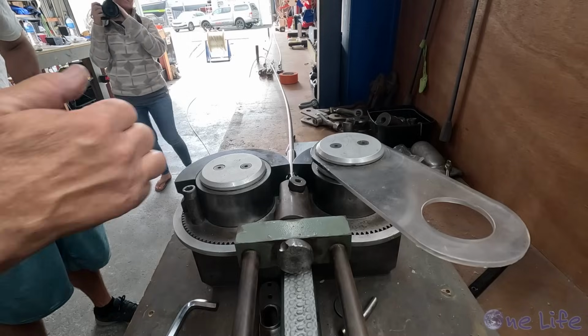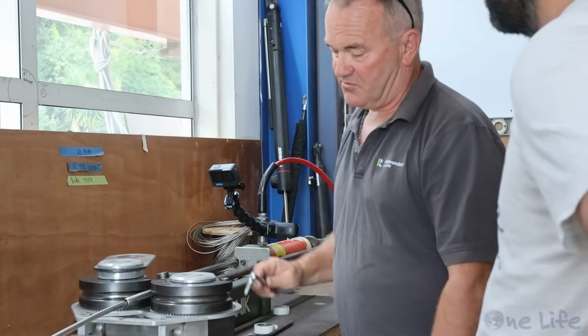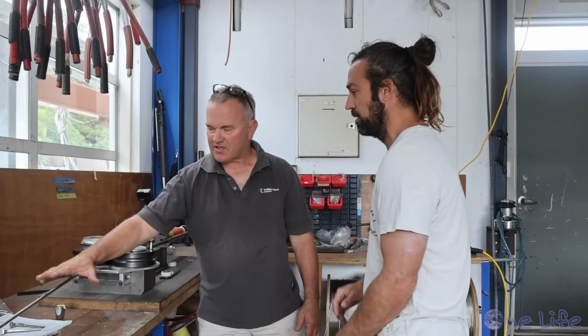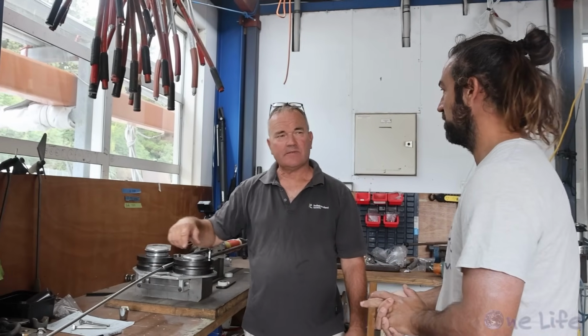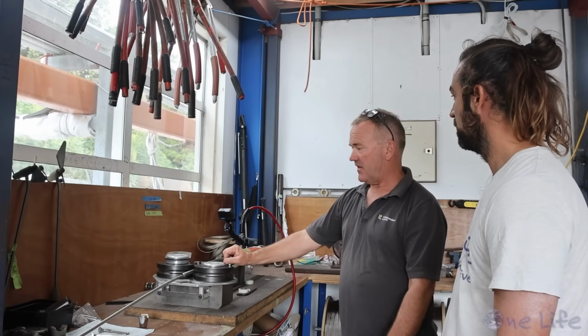We'll roll this through once full, and we'll rotate, and we'll do about 2/3 of the flash on the other side. We'll roll it twice. That's just what we do. And after it's swaged, that will hold the same force as the wire, like 100%. Oh yeah, higher breaking strength than the wire. The wire's going to bust well before that. That will never pull out. Wow, okay. That always breaks the wire first. Every now and then you want to do a pull test and take it to guys to do that.